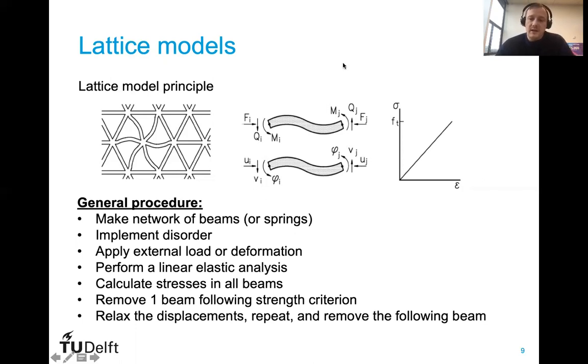We assume that each element has an ideally brittle behavior, so that it has a linear relation between the stress and the strain, and it fails in a brittle way. We then perform a linear elastic analysis of the whole system. We calculate stresses in all beams, and then we identify the beam that has the maximum stress to strength ratio. This beam is then removed from the mesh, thereby creating a small crack. After that, we relax displacements and repeat the whole procedure once again. Remove the following beam. This way, we can simulate crack growth in our cementitious material.